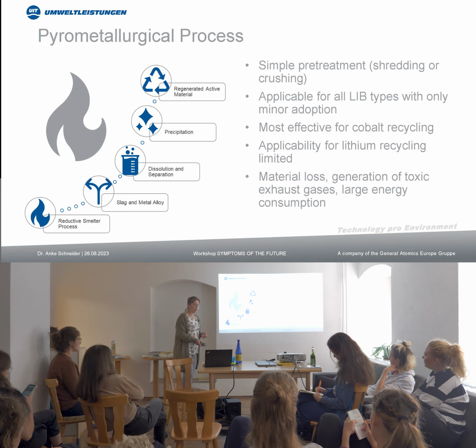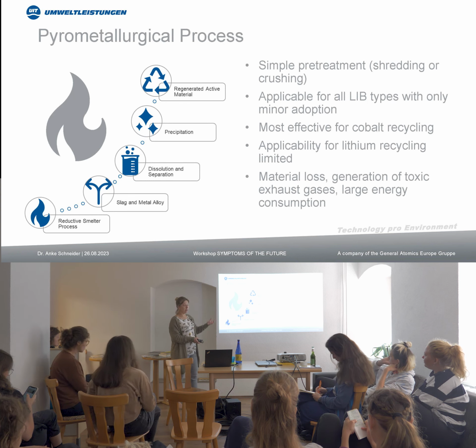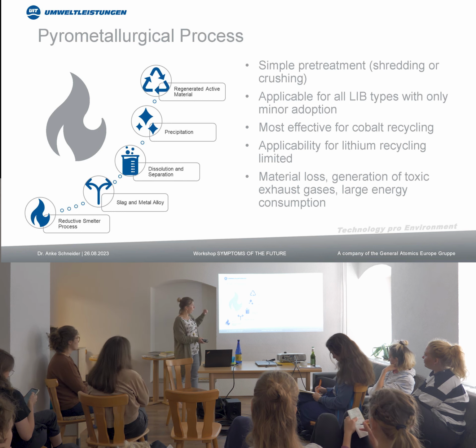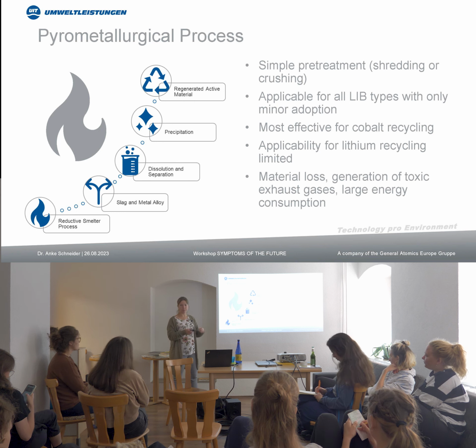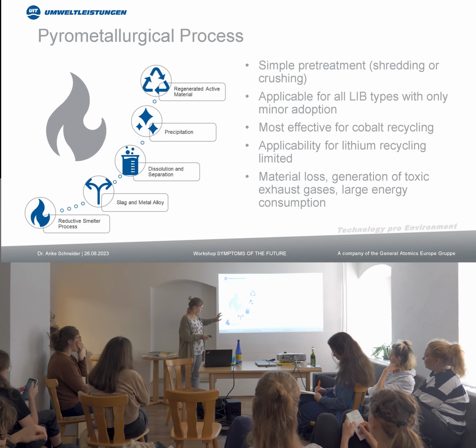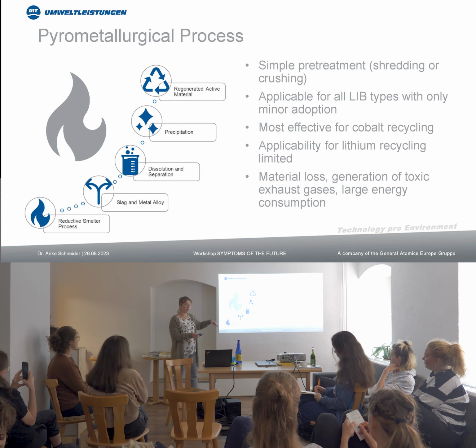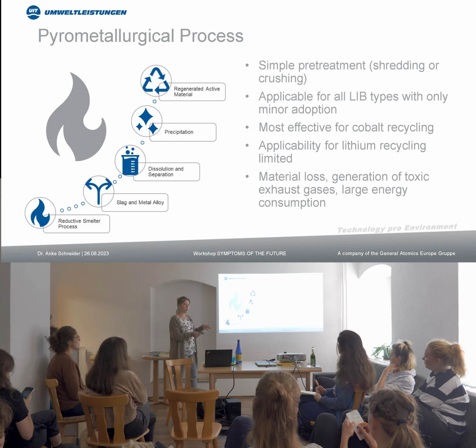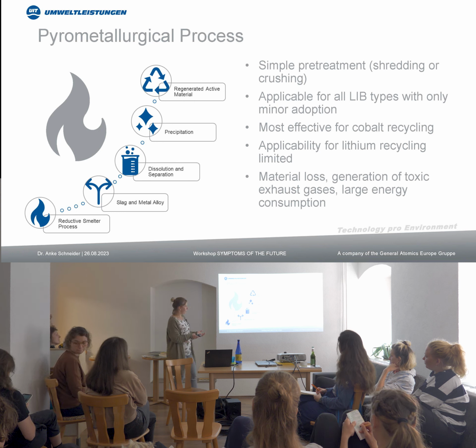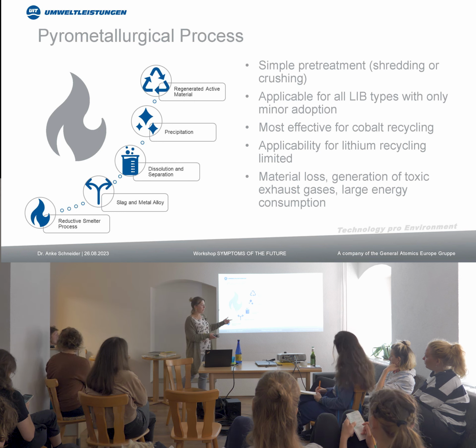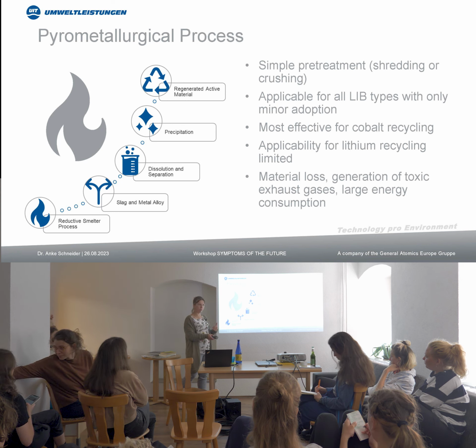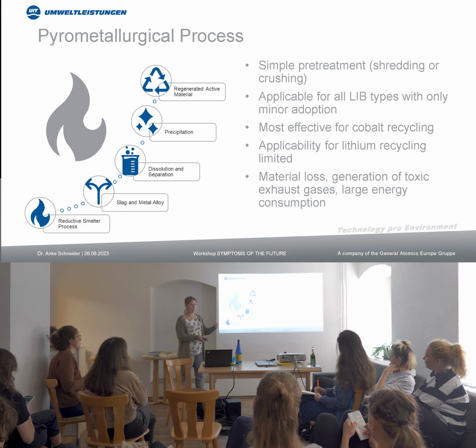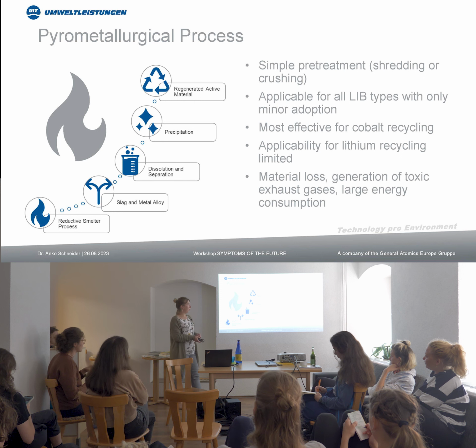The next one is a pyrometallurgical process. As the name says, pyro, it's a hot process. So you have a very simple preparation. You just get rid of the plastics around the batteries until you have the single cells. Then you just crush them and put them into a big oven. And I think this is the technology, to be able to drive this oven in a way so that the recycling works after that. From this oven, you get a slag and a metal alloy. The metal alloy is containing cobalt, nickel, manganese. This can be easily recycled into battery materials.